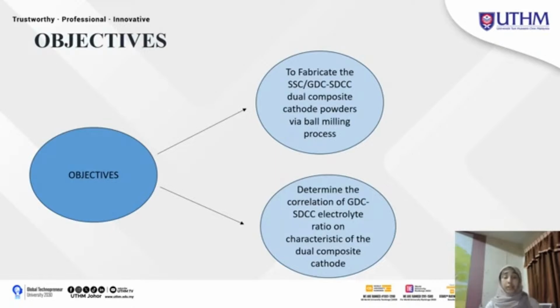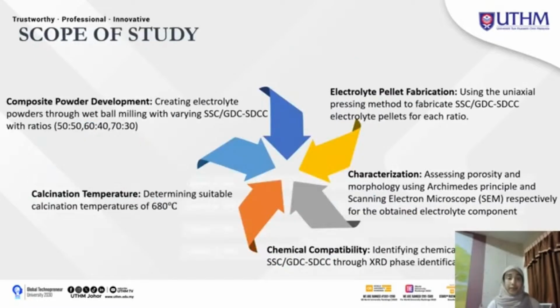Next is to determine the correlations of GDC, SDCC electrolyte ratio on the characteristic of the dual composite cathode. Scope of study about this project. The first one is the composite powder development, which will create the electrolyte powders through the wet ball milling process that I have already highlighted before, with varying SSC, GDC, SDCC with ratios 50-50, 60-40, and 70-30. So these three ratios will give me three different results, because it will go through the wet ball milling process depending on the ratios. So it will be a repetition of the process according to my ratios.